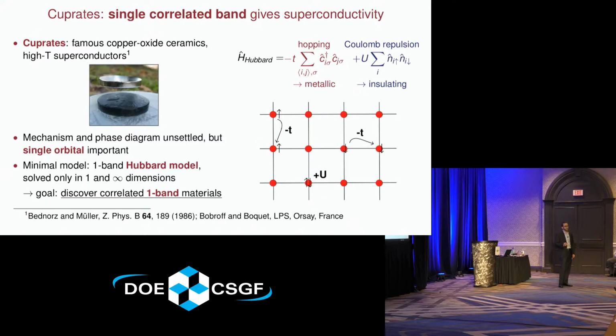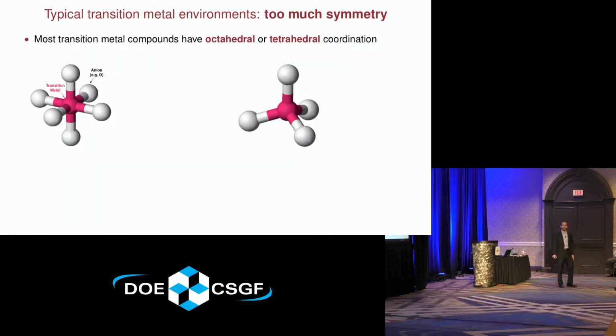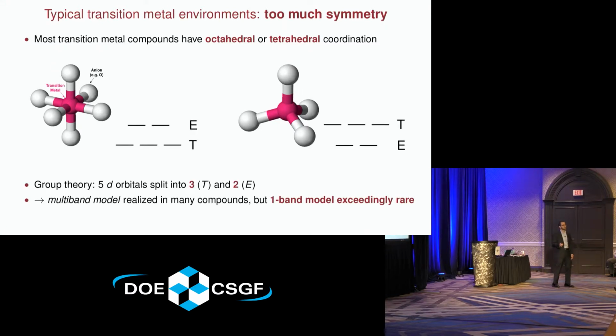So why is that so complicated? It sounds simple, just one band. And the reason is basically, in most transition metal compounds, you really just have too much local symmetry. So the coordination of most transition metal compounds is either octahedral or tetrahedral. And just from group theory, from symmetry, that splits the 5 d orbitals into a group of 3, which we call T, and a group of 2 called E, for both of these cases. So essentially, because you have this high symmetry and you have this high degeneracy of these d orbitals, we've realized many multi-band Hubbard models in practice in many transition metal compounds, but a one-band model is really exceptionally rare.